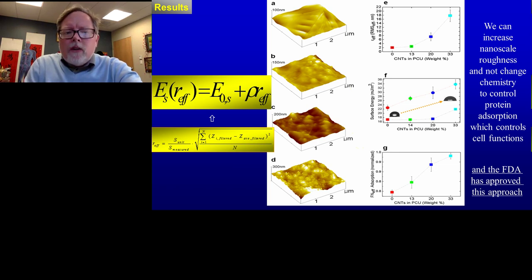So our equation, over here on the left part of the slide, involves three key terms. The first term, pictured as E sub S, is the energy of the protein that you want to adsorb. So if it's mucin, because mucin reduces bacteria attachment, then the energy of mucin is what you would put in E sub S. The next term, E sub 0, comma S, is the starting energy of your material. So this is the flat version of your material. On the slide, A is a flat version of a polymer that is used in many medical devices. That polymer is called polycarbonate urethane.